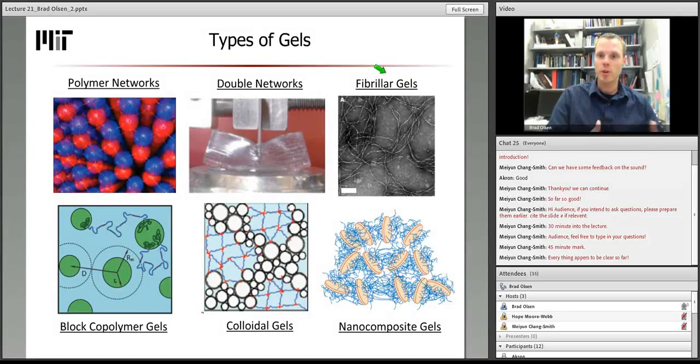Some of them are proteins, some of them are pi bonders, some even very, very small peptides, for example, with optically active functionalities connected to them. Some can be hydrogen bonding moieties, or some can even be lipids. They self-assemble into long fibrils, and the fibrils can form either defects that result in junctions or physical entanglements around one another, or some combination of the two that result in gelation in the system.